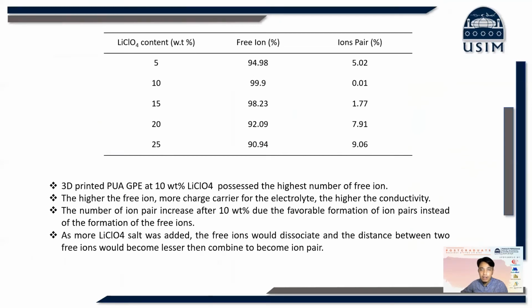This is the summary of the previous graphs. The 3D printed PUA GPE at 10% lithium perchlorate possesses the highest number of free ions. The higher the free ions, the more charge carriers for the electrolyte, the higher the conductivity. The number of ion pairs increased after 10% due to the favorable formation of ion pairs instead of the formation of free ions. As more lithium perchlorate salt was added, the free ions will dissociate and the distance between two free ions will become lesser and then combine to become ion pairs. Then the number of free ions also decreased and the conductivity also decreased.